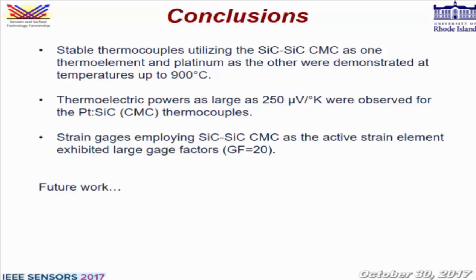For future work, we need to improve the performance of the thermocouples by 100 degrees to get it to 1000. The big thing about the strain gauges is that all the testing that was done was at room temperature. So we actually need to test this at higher temperature because this is going to be advertised as a high temperature strain solution for the CMC material. The only issue is that our strain rig is too big to fit in a furnace. We know the equipment we need, it's just a matter of funding.